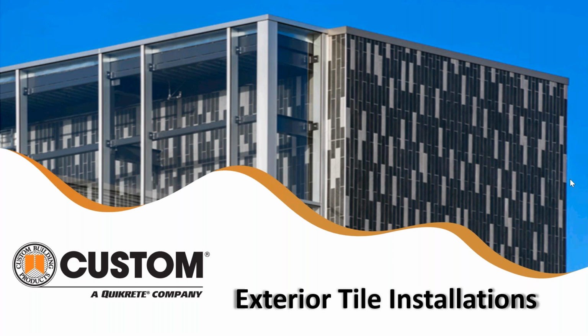For example, the International Building Code says for brittle surfaces, which tile is one of those, out of plane deflection for walls should be no more than L/240. However, the tile industry always recommends a deflection of L/360. And just to complicate things a little bit more, the Natural Stone Institute says if you're using a natural stone on a stud wall, either metal or wood, they need an L/720 deflection. So it not just becomes responsible to the designer to know which code he's applying, but also which material is going to be applied to that wall. That's just one of several considerations that need to go into that conversation with that specifying entity. So the sooner that those two parties can get together, the better and more successful that installation is going to be.